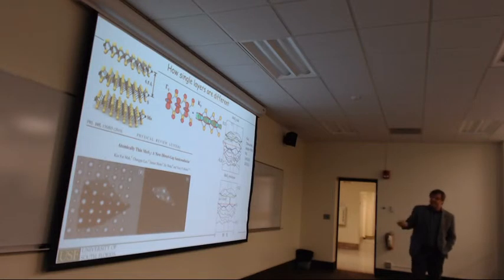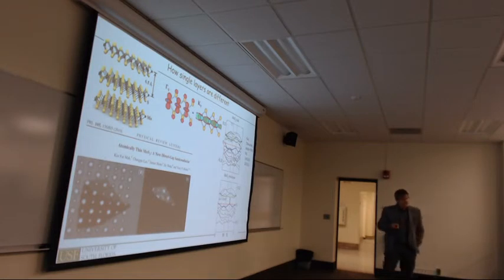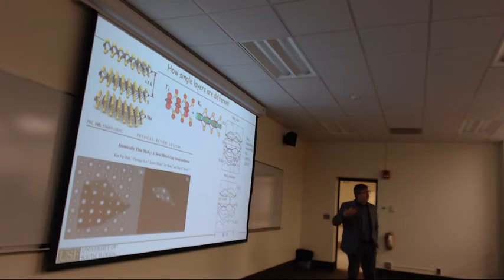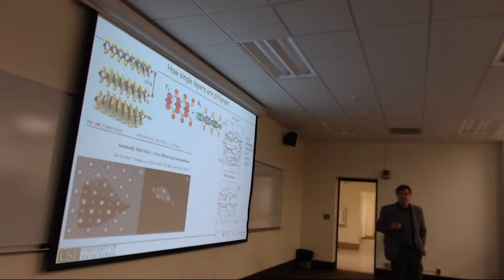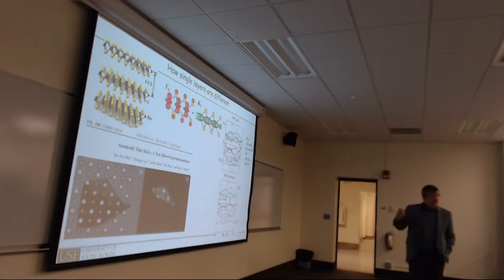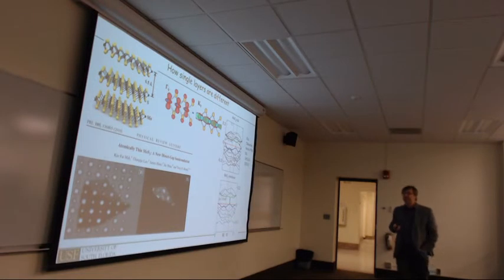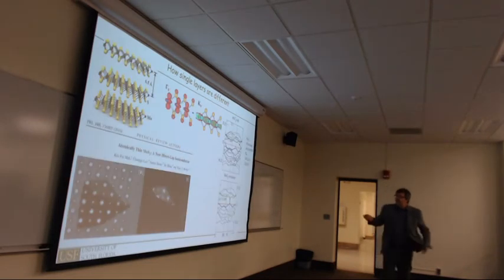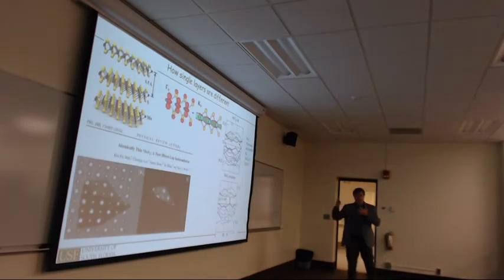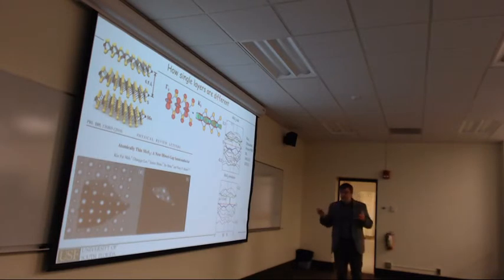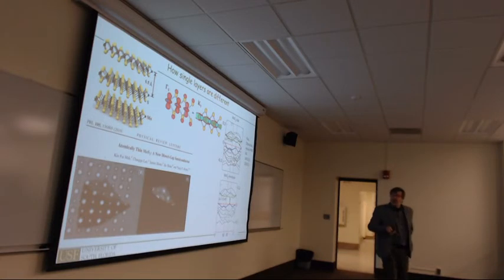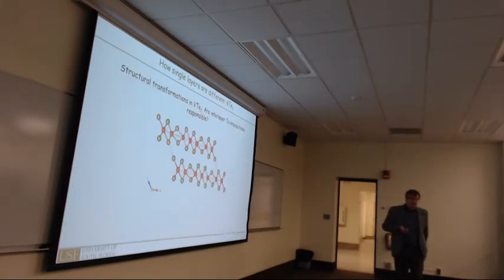So the change from indirect to direct bandgap material is really a consequence of the interaction of the molecular orbitals in the planes, where only part of the band structure interacts strongly between the different layers, while another part of the band structure does not. Now, this is a very nice example why monolayer materials can have very different properties than bulk materials in the electronic structure. Now, we ask, can there also be structural variations due to interlayer interactions?